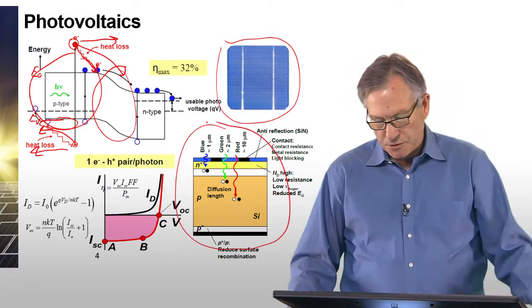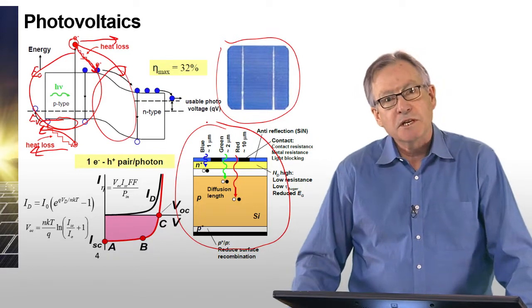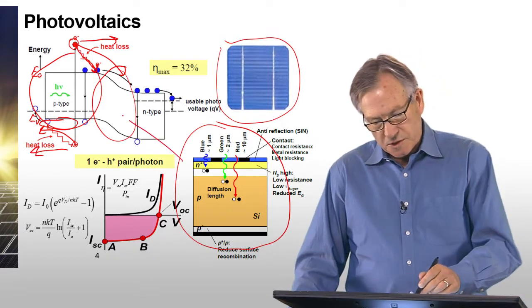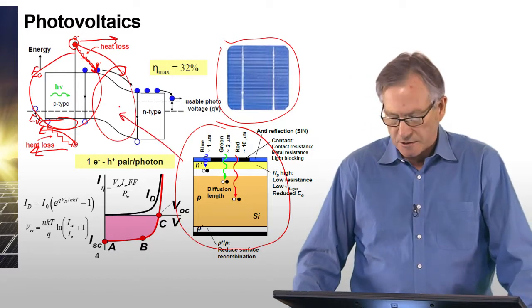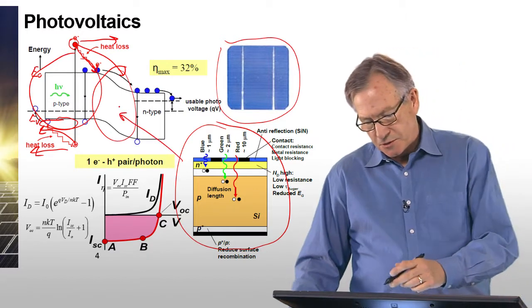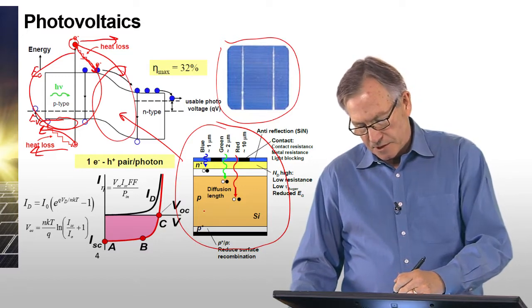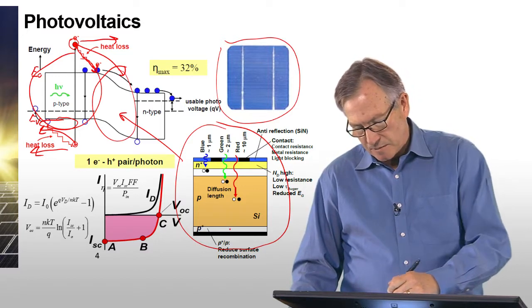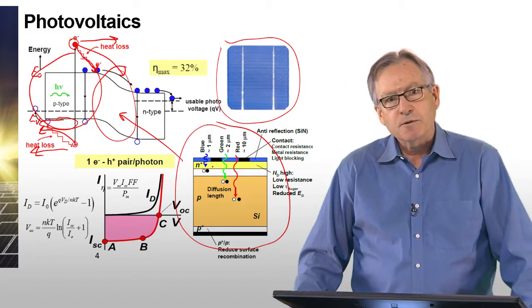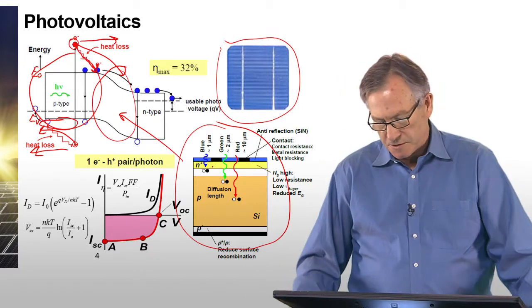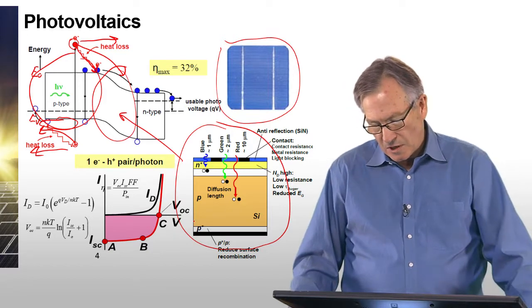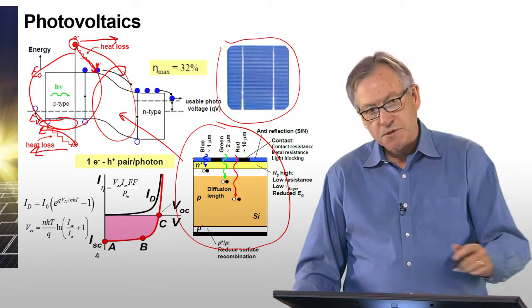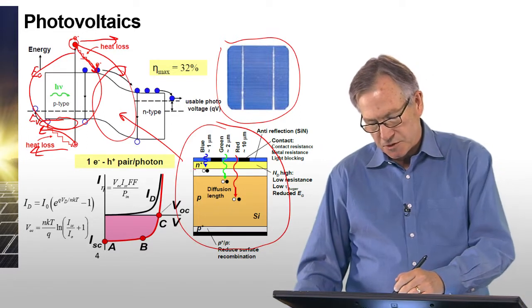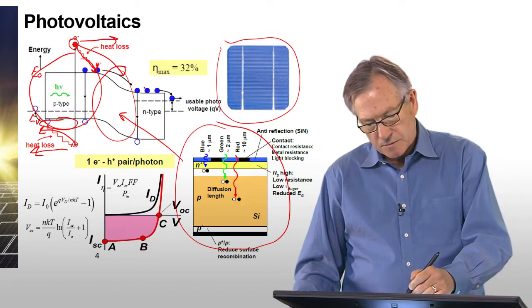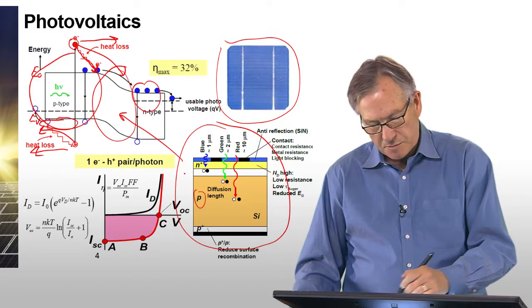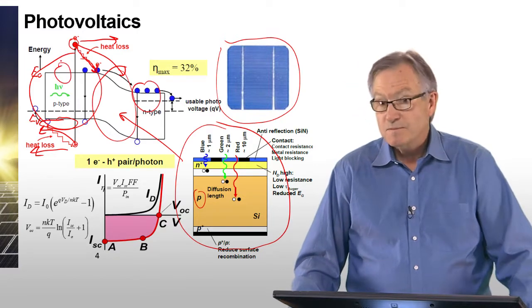This is a cross-sectional view of a p-n junction solar cell. It corresponds to the picture that I showed here energetically, but what it shows is the structure. Let's start at the bottom. It starts with a silicon wafer, which is about 150 to 200 microns thick, which is doped p-type. And on top of that is grown or diffused n-type material to form the p-n junction. So what's shown here is the n side, which is this side over here, and here's the p side, which corresponds to this side over here.